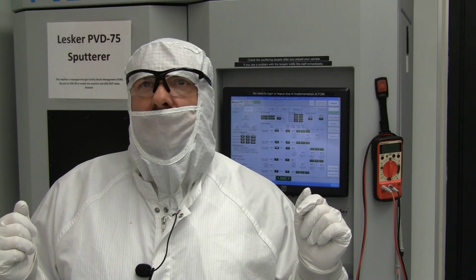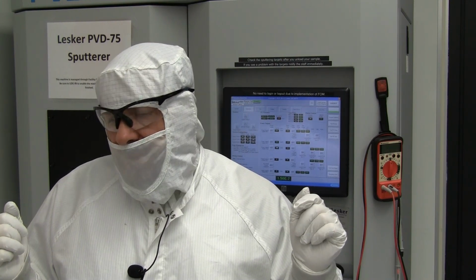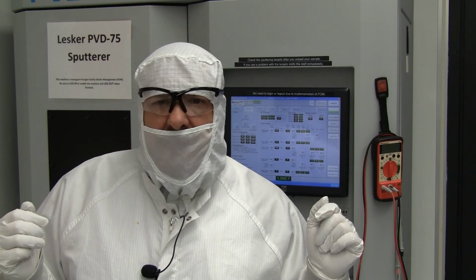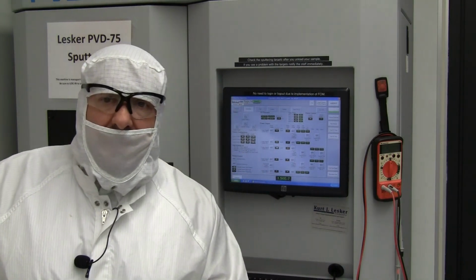One popular film that's done is indium tin oxide. So that's widely done for all your displays, TFTs, thin film transistors. So it's a conductive film that is transparent. And that's tricky to make. You really got to tune it, and then you got to anneal it to get your conductivity up. If you ever buy conductive transparent slides, they can be quite expensive. It's because the process is tricky. So at any rate, that's one case where that's used.